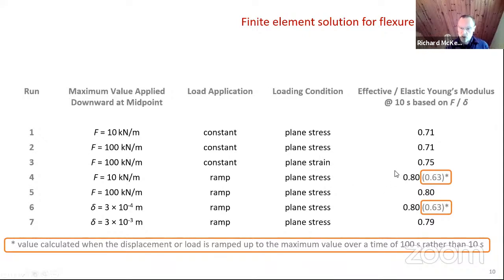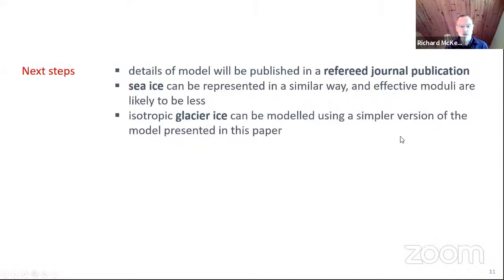One thing of note, just looking at all the results: the effective over elastic modulus for all the four ramped values, whether it's ramping a load up or a displacement up, you can see that the ratio of effective to actual Young's moduli are essentially the same. And basically what that means is that the delayed elasticity is responding quite quickly, and quicker than the time over which that load is ramped up. There's a lot in this, and there's a bit more discussion in the actual paper.